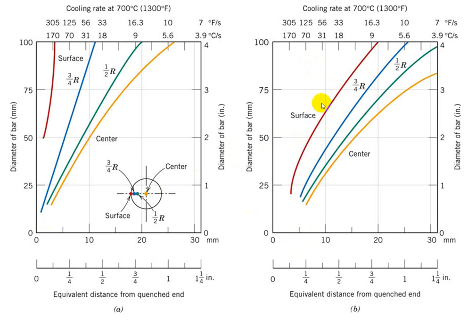And then the next important thing is how do we plot the cross section hardness profile? So this is very important. In this case, all we need to do is we first define what is the diameter of our bar, we pick four locations: center, half, three quarter, and surface with respect to the cross section. And then we calculate or get from the chart what are the cooling rates at those spots for that bar. We know the alloy, we go to that particular alloy chart, and then we find the hardness.